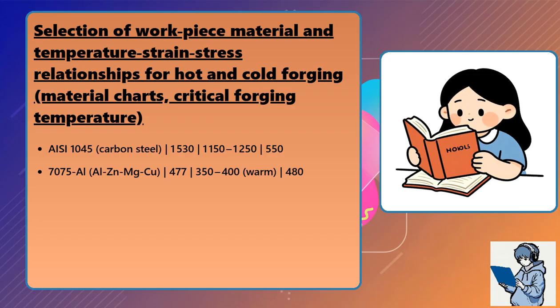7075 aluminum, an aluminum zinc magnesium copper alloy, melting point 477 degrees Celsius. Recommended hot forge temperature 350 to 400 degrees Celsius, considered warm forging. Typical yield strength cold, 480 megapascals.